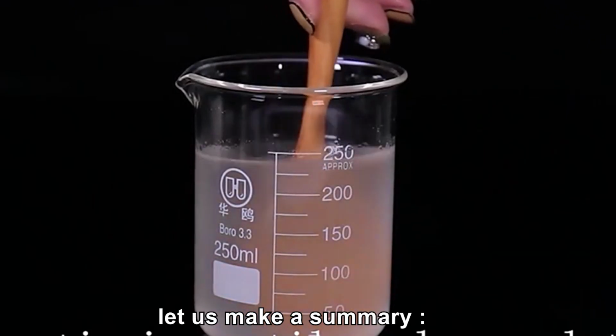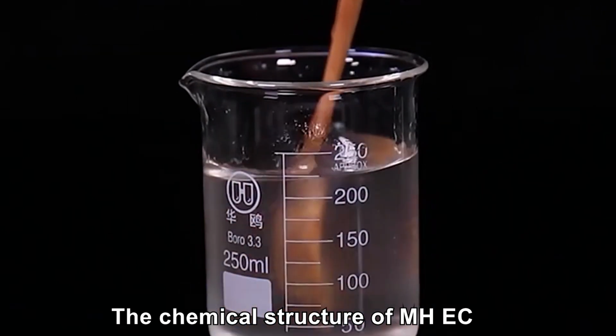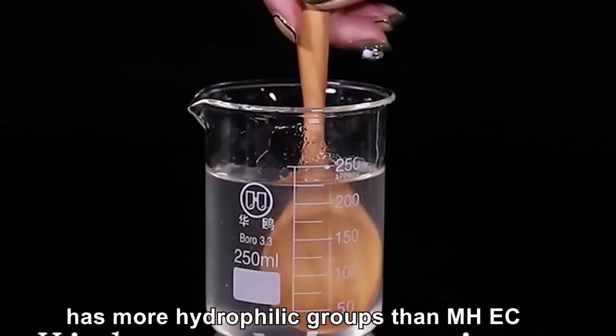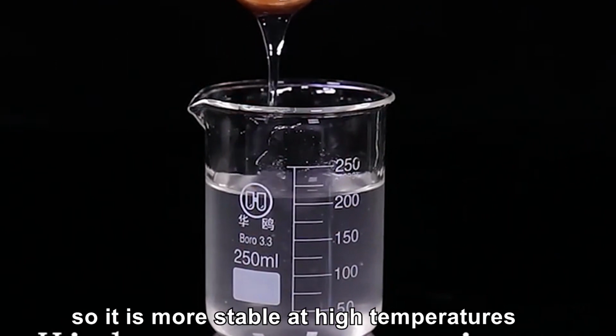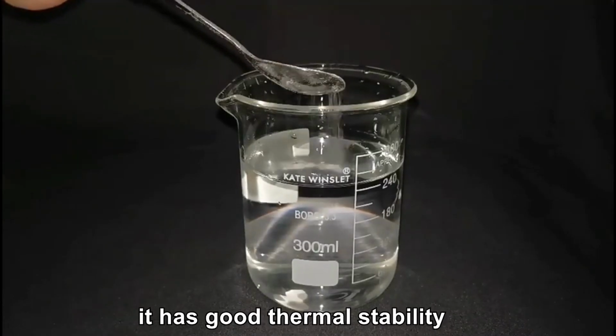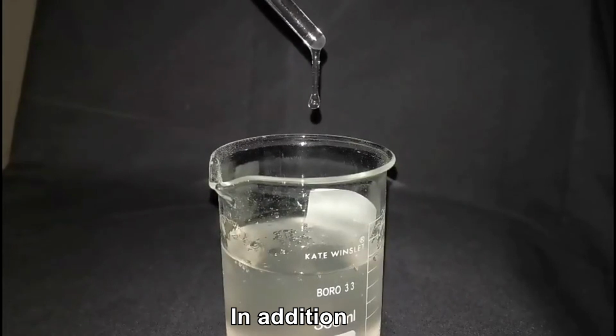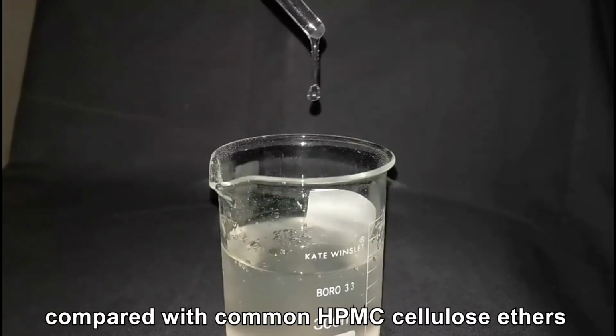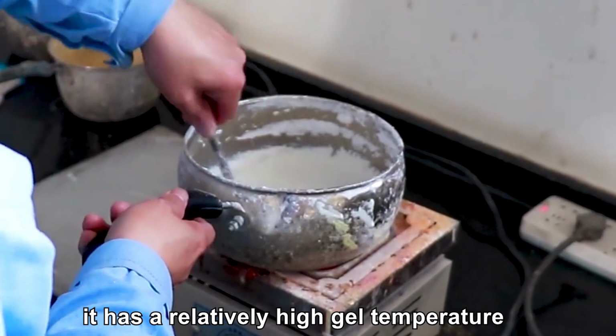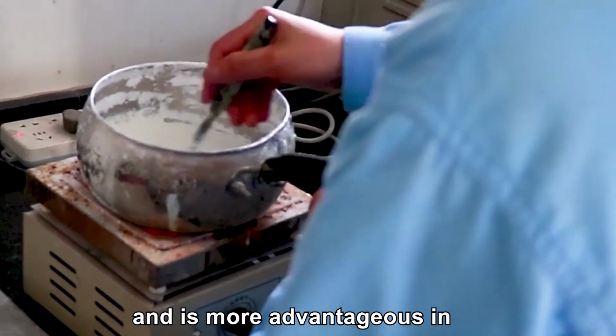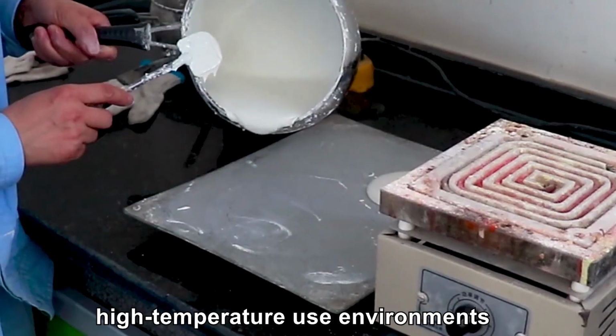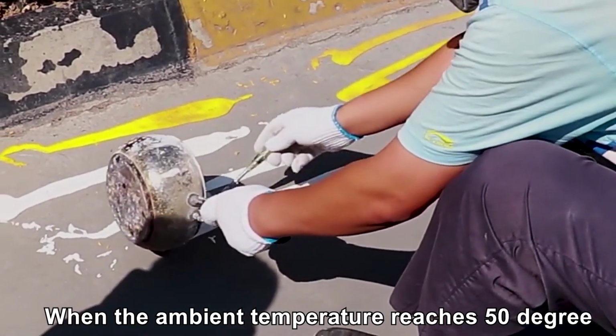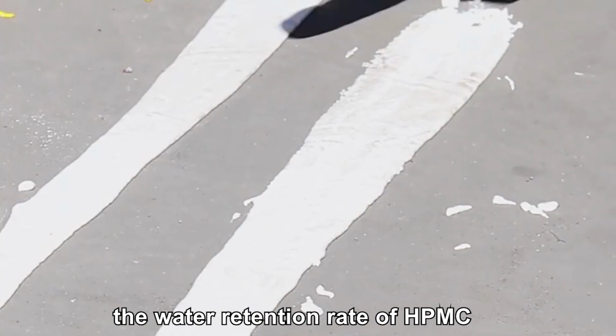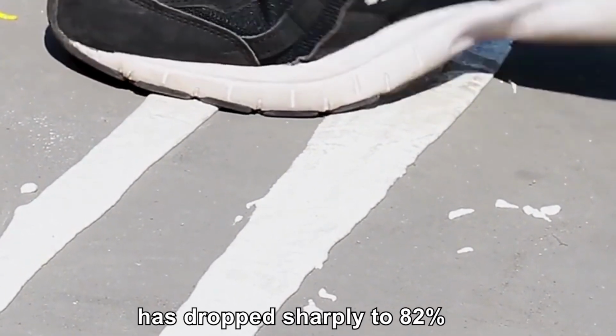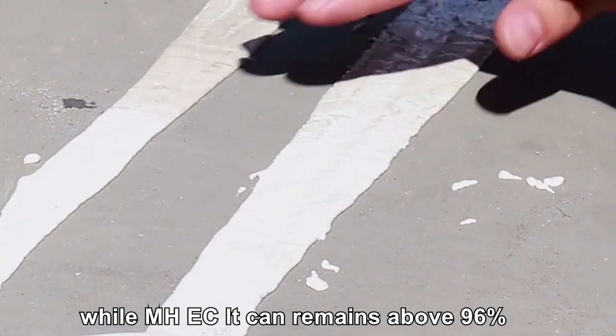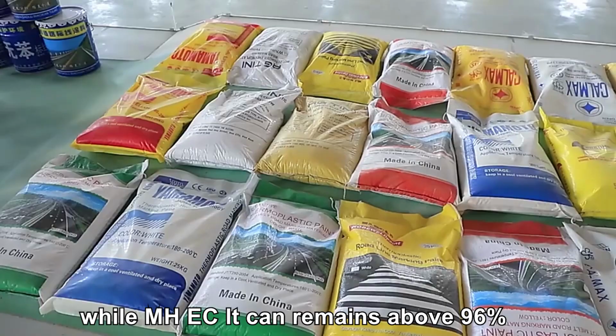Let us make a summary. The chemical structure of MHEC has more hydrophilic groups than HPMC, so it is more stable at high temperatures. It has good thermal stability. In addition, compared with common HPMC cellulose ethers, it has a relatively high gel temperature and is more advantageous in high temperature use environments. When the ambient temperature reaches 50 degrees, the water retention rate of HPMC drops sharply to 82%, while MHEC can remain above 96%.